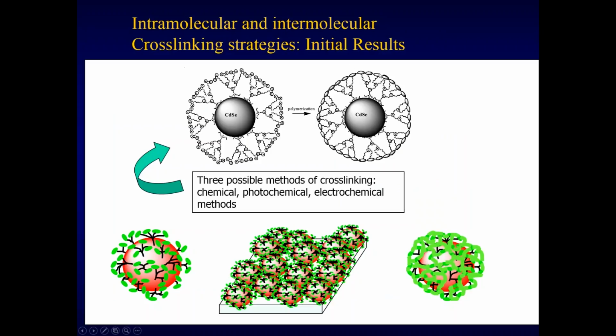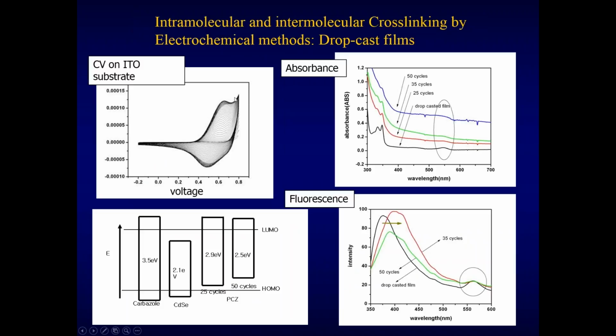Now, what's interesting is that if we compare the HOMO-LUMO properties of the carbazole and the cadmium selenide, cross-linking of the carbazole to polycarbazole units increases the HOMO, or the highest occupied molecular orbital. Now this value here may seem insignificant based on just the fluorescence properties alone, but actually it's a very important property when it comes to the preparation of light-emitting diode devices, because this can translate to lower turn-on voltages.